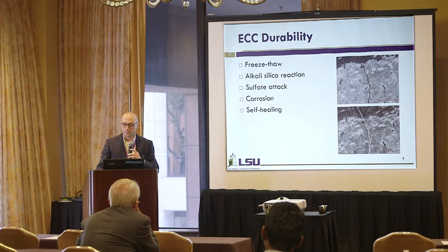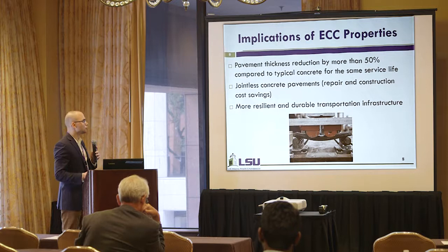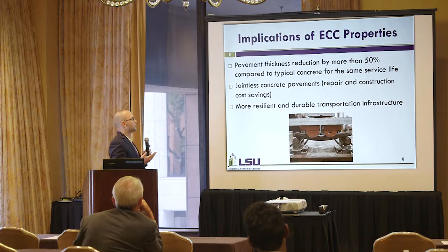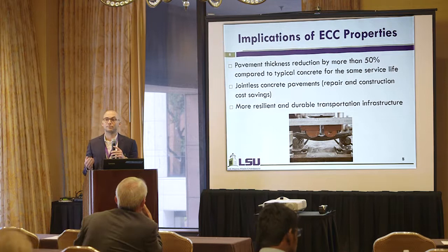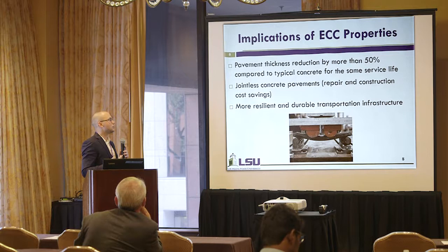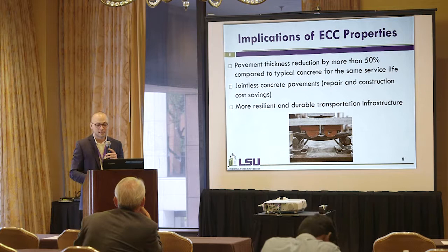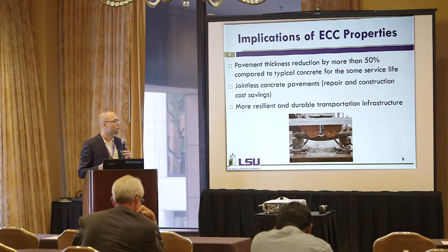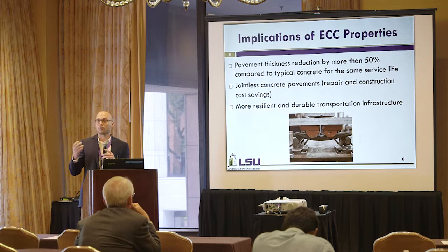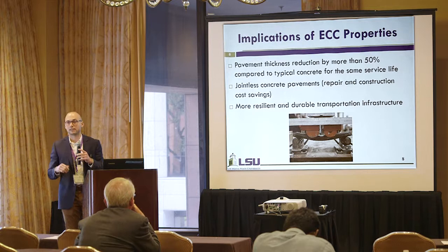So what are the implications of all these properties? First, pavement thickness could be reduced by more than 50% — a factor of two — which is remarkable. In addition, the possibility for jointless concrete pavements is real with these materials because of the amazing ductility — tensile ductility about 100 to 500 times that of typical concrete. It will also provide more resilient and durable transportation infrastructure because of the great resistance to major deterioration mechanisms like freeze-thaw, and because it is a self-healing material.